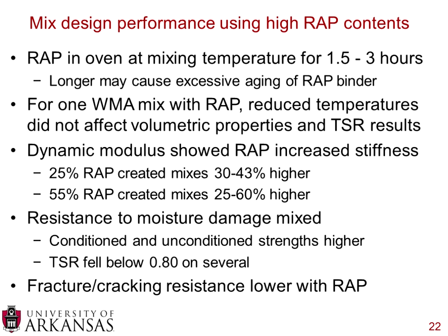I think I said that backwards. I apologize. The tensile strength ratio is the ratio of the conditioned to the unconditioned strength. Generally, conditioning the sample, introducing that moisture, reduces the strength, so your tensile strength ratio drops under 1. And in order to pass the specification, you need to have a tensile strength ratio of above 0.80, and that's a ratio of two tensile strengths.